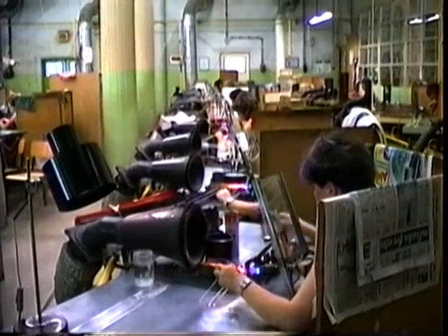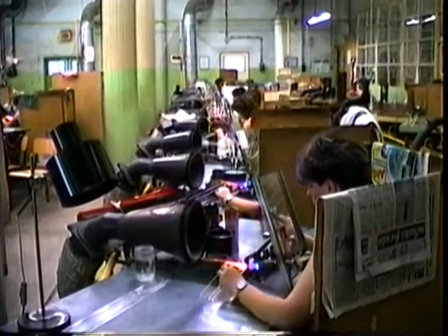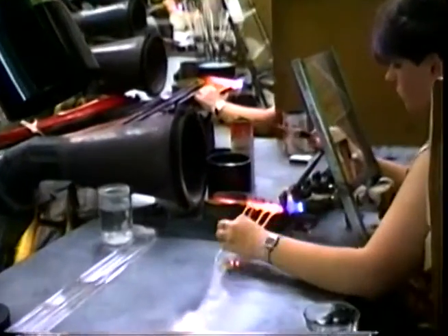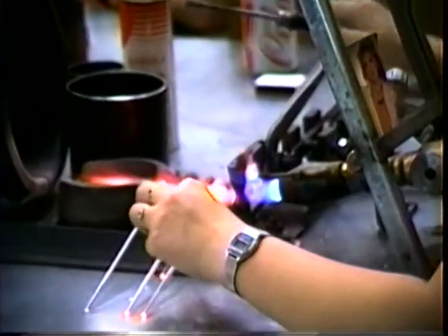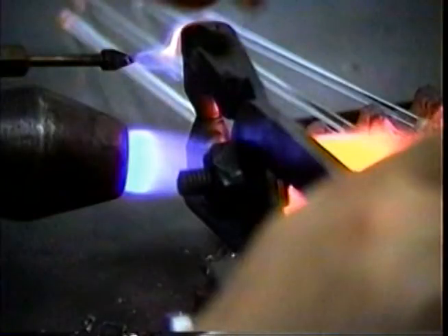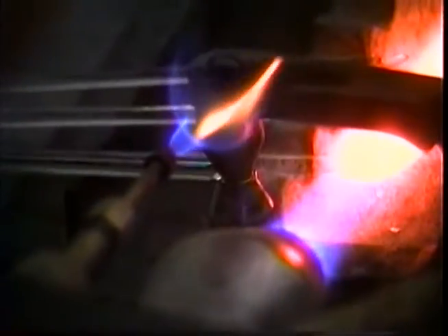This is the workroom with their exhaust system. Each person has their own workstation with space dividers behind them and their own vacuum system. This first person is making pressed glass stones. Note the separate torch tip for heating the dies. She moves the glass rods down the notches of the cast iron form 4 at a time. Very efficient for increasing production.